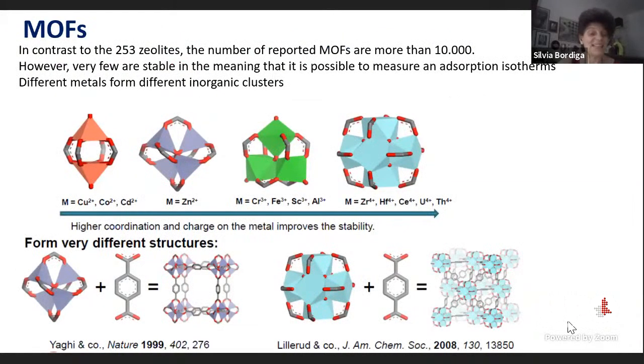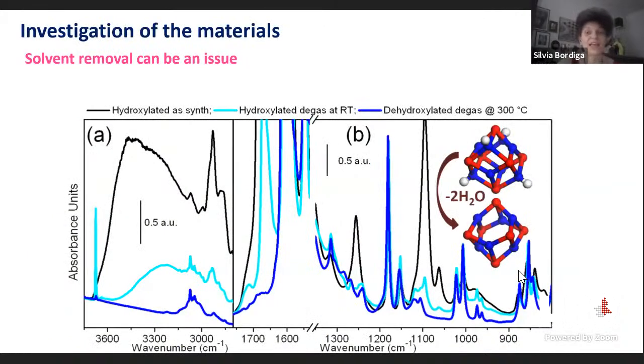So at the end, the structure can have cations which have a fulfilled coordination sphere, or a structure where we have cations with a coordination vacancy, and so where we can have some chemistry already at the node. Then we can open the possibility to make, in a precise way, systems with defects, selectively removing some linkers, and so starting to play with the chemistry of the lattice. However, one important point at the end of the synthesis is to be able to remove the solvent. And this is not an easy task.